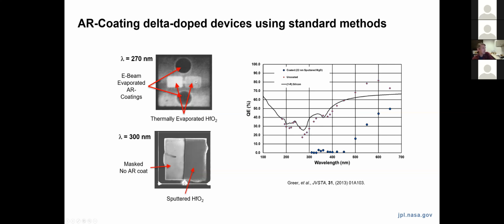So light here means that the response was increased over the uncoated regions, and dark means that the response was degraded in some way. So you can see, for example, that for E-beam evaporated coating, which may generate X-rays, which are sort of detrimental to the backside of the device, or physical damage that you might get from sputtering, the application of the anti-reflection coating, which was expected to improve the performance, actually made the performance worse.